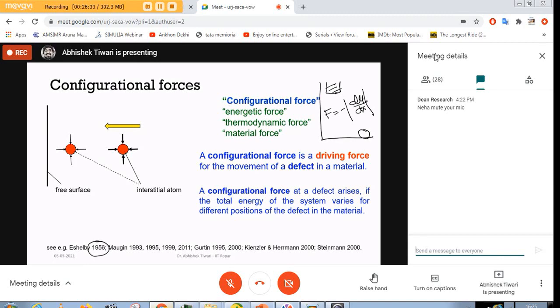So if you assume an interstitial atom inside a material, I will not call this interstitial atom very sad, but it is also not in the happiest situation because there are bigger atoms which are trying to compress it. They don't want it. They want the void to be void. And if this interstitial atom goes to the surface, at least half of the side will be compression free. So there exists a situation where this atom can be a little happier, and therefore there will be a force on it which will compel this atom to go to the surface. Whether or not it goes to the surface depends on whether there is a path provided to it. And that is in a nutshell what configurational forces are.